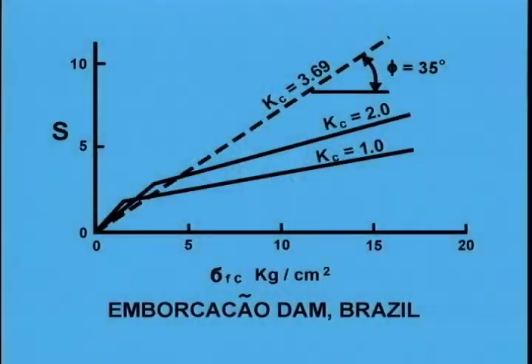The undrained shear strength of a soil is directly dependent upon the normal stress on the failure plane and the ratio of major to minor principal stresses at the time of consolidation. It is a consistent and logical way to define the shear strength. The results of ACU tests at a principal stress ratio K sub C equal to 2 performed on the core material for the Emborcação Dam in Brazil are shown here.